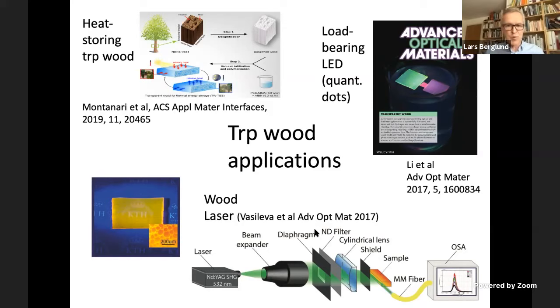For instance, you can add quantum dots and create load-bearing luminescent materials. What we're aiming for there is white LED light, that light sources that can carry load. You can also use it for waveguiding. The group of Sergei Popov and colleagues in Kista have worked together with people in our group to create this laser. It sounds like science fiction, but it's actually quite interesting and has many applications. Another application is heat storage. Celine Montanari has used phase change materials. And perhaps the most interesting there in a nanostructural point of view is that the polyethylene glycol that has the function of phase change material that stores heat is impregnated into the cell wall. So we're really using the nanostructure.